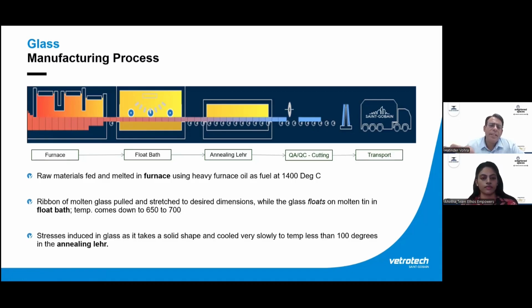And here the temperature is close to 650 to 700 degrees Celsius. From there, it will go to the annealing lehr, where we cool the glass gradually. Then it goes to QC, where automatic laser detection is there, and cutting will happen. And then packing and transportation will happen. So this is the basic model of how glass is made.